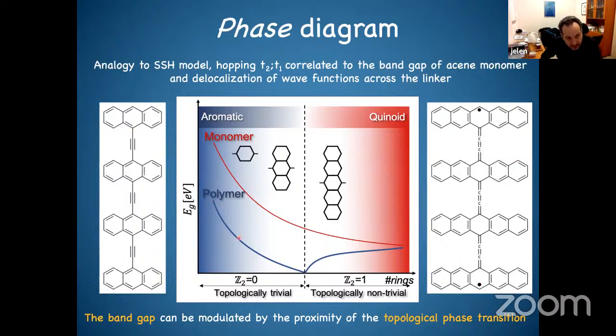And moreover, when I start to tune the size of the system, because I told you if I go from one topological state to the other, I need to reduce the band gap. And that's a very interesting property, because now I can design a polymer which will be almost conductive. There is a question if I can reach really conductive polymers, but this means that now I don't need to introduce extra heterogeneous atoms in the polymer. I can just make these polymers conductive, at least at room temperature, just by designing the polymer to be very close to the topological phase transition.